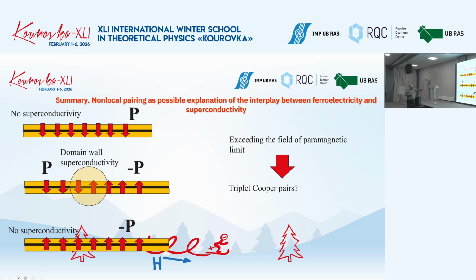Another important thing is that this kind of interlayer superconducting correlations can favor triplet Cooper pairing. And this can help us to explain the high critical fields exceeding the paramagnetic limit, and in principle, twofold anisotropy. To be honest, it's not the only way to explain twofold anisotropy, but anyway, this seems to be the case.